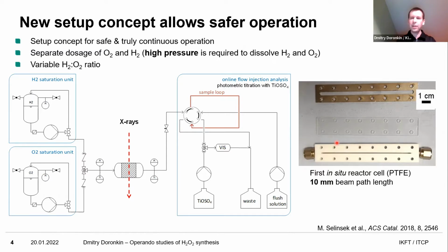Since we are not dealing with gases, but with liquids, and that means we have high viscosity, high pressures, we expect to have movement in the catalyst bed. That's not what we want to have for X-ray absorption studies. Of course, we want highly homogeneous samples for transmission. But let's face the facts. If we want to run it on real reactors, we have to live with compromises. So at least it's good that we can see what's happening, also with a camera.